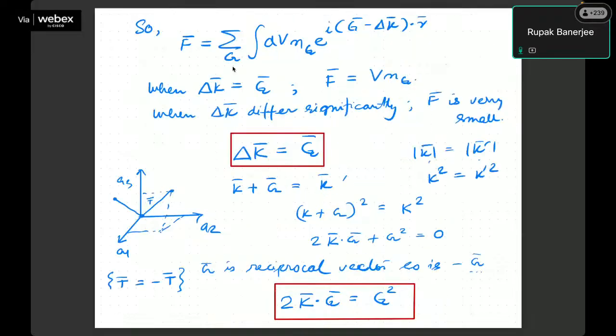So what do you get? You get the summation over G, you get the integration dV n_G e to the power i (G minus delta k) dot r. So you see, you have now the reciprocal lattice vector G, the scattering vector delta k, and on the condition when delta k equal to G, this becomes 0 or 1. And if you integrate, your total scattering amplitude is now nothing but the number density times the total volume. So this is per unit volume, this is total volume. So your scattering amplitude must be this, right? How many electrons scattered over the total volume.